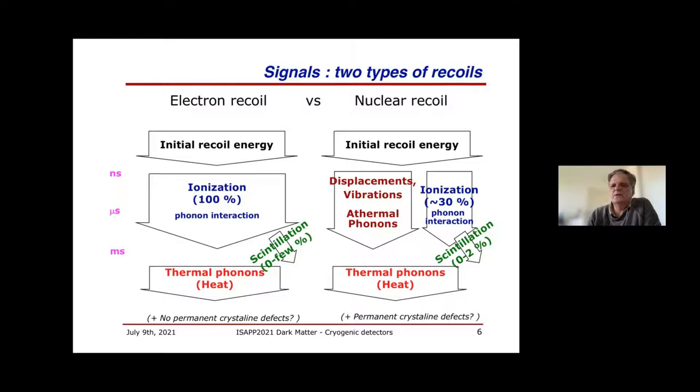And this will push a much bigger part of the energy directly into what is called the nuclear stopping power, which is basically that the energy goes directly to the lattice, or directly to the displacement of other atoms and other ions. Now, a phonon is just a term to describe the degrees of freedom of the lattice vibrating, so this means that a nuclear recoil is very efficient at putting a lot of energy in the phonon channel.